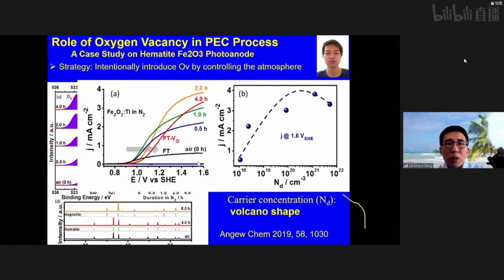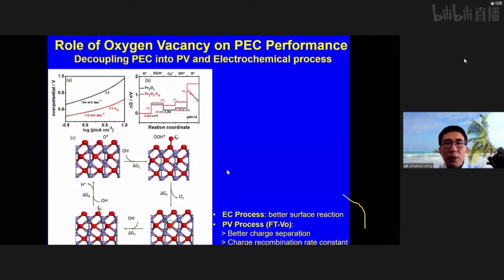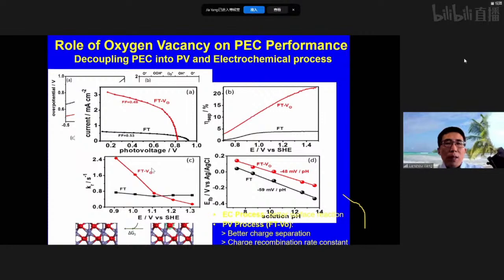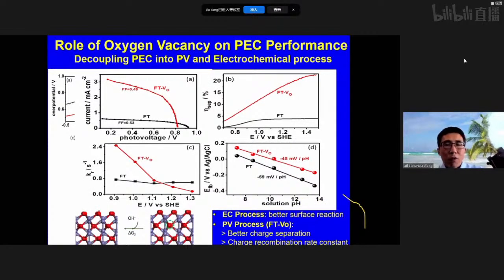And then we started to look at these two decoupled processes. The first is the surface reaction, which is basically an electrocatalytic process. We used a number of characterization tools, including simulation tools, to understand it. We found that the introduction of oxygen vacancy on the surface can lower the formation barrier of oxygen and give faster kinetics. Then we continued to look at the PV effect, the photovoltaic effect, and this effect is more interesting.